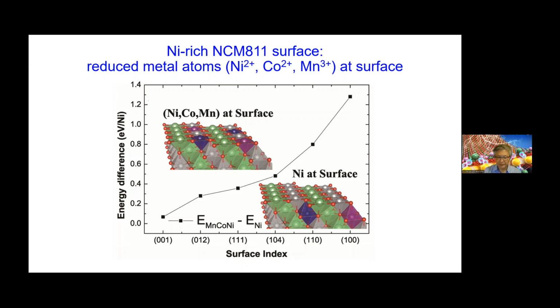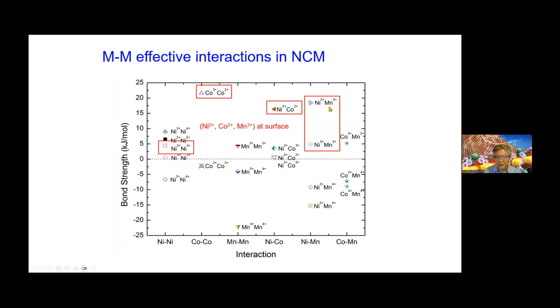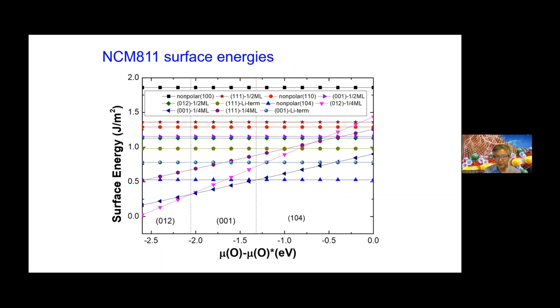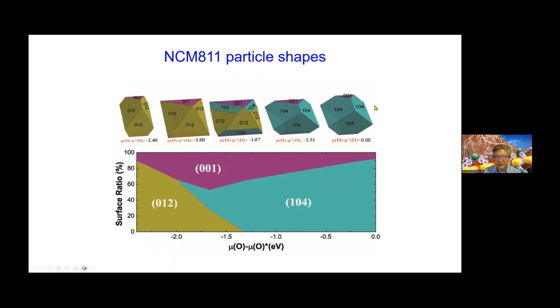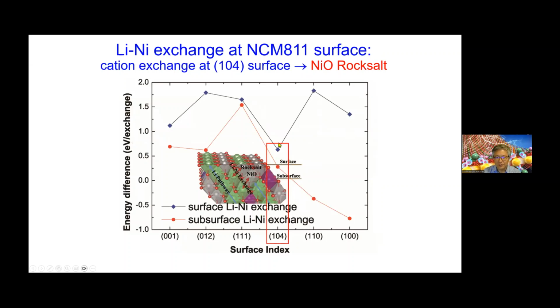So from the surface point of view, the cathode material is behaving like pure lithium nickel oxide. The driving force is that on the surface, nickel-nickel interaction is more stable than nickel-manganese or nickel-cobalt. That's the basic reason for the energy diagram we mapped previously. Based on that, we can look at the surface energy and shape evolution. Without getting into too much of that, this leads to surface phase evolution to nickel oxide. You see that this oxide layer was lithium metal O2.